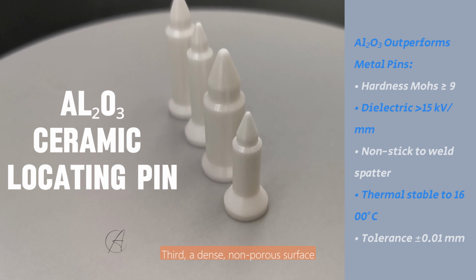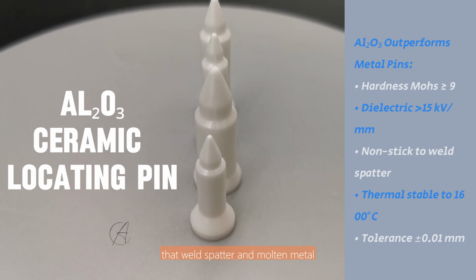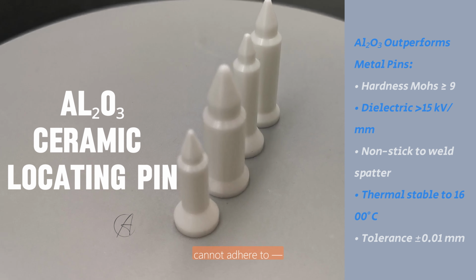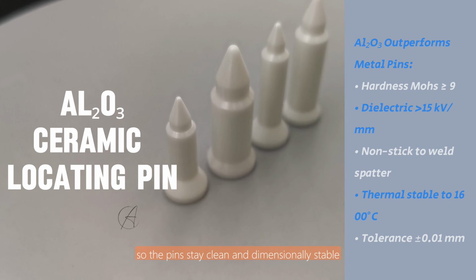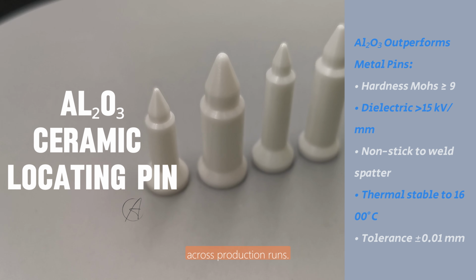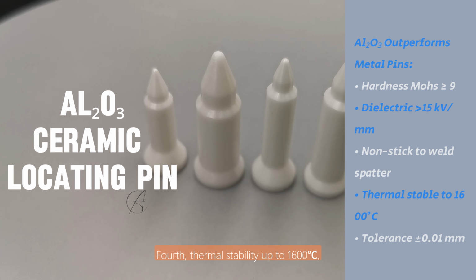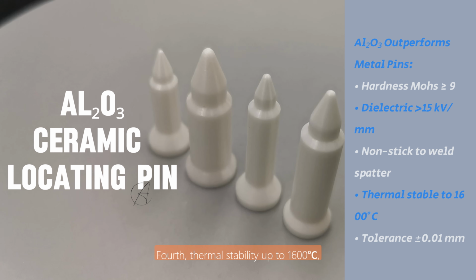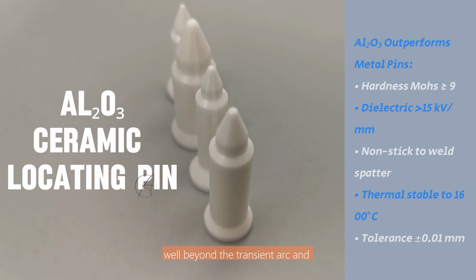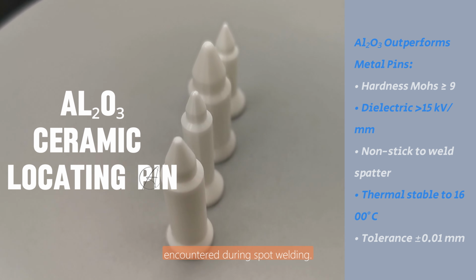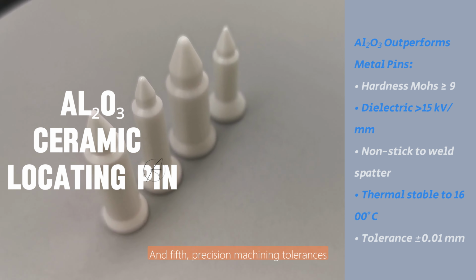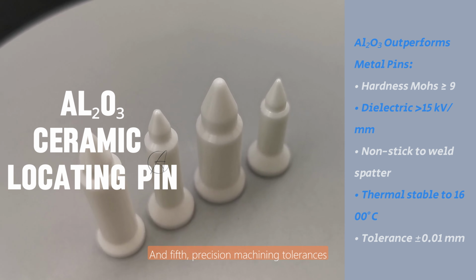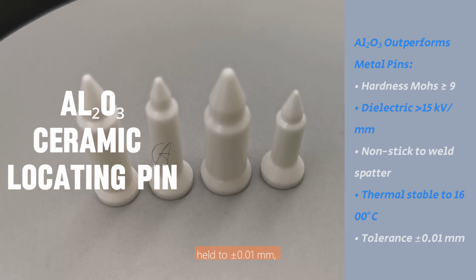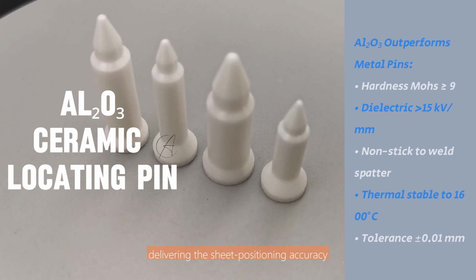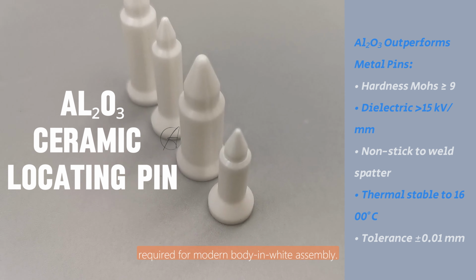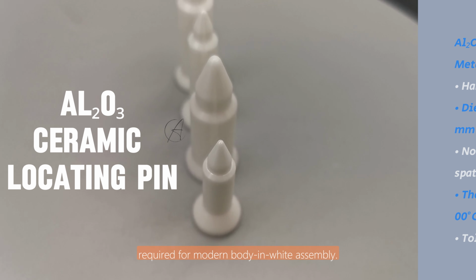Third, a dense, non-porous surface that weld spatter and molten metal cannot adhere to, so the pins stay clean and dimensionally stable across production runs. Fourth, thermal stability up to 1600 degrees Celsius, well beyond the transient arc and spatter temperatures encountered during spot welding. And fifth, precision machining tolerances held to plus or minus 0.01 millimeters, delivering the sheet positioning accuracy required for modern body-in-white assembly.